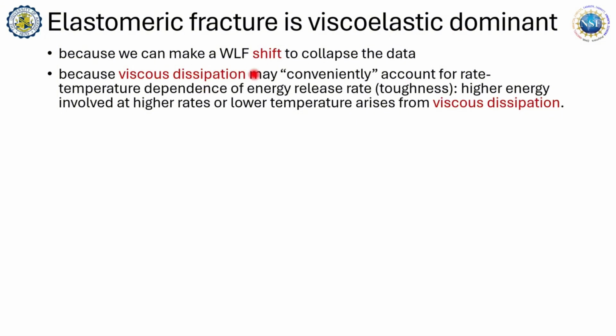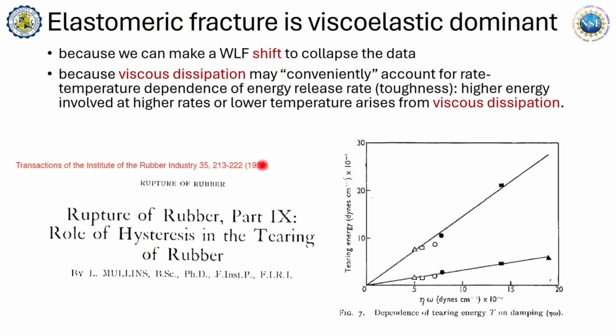Secondly, well, this so-called viscous dissipation, of course, is higher at higher rate and a lower temperature. Therefore, it conveniently seems to describe the rate dependence and temperature dependence of my resistance to fracture. That viscous dissipation will tell you. So in fact, one of the papers, 59, shows that it's just related to how viscosity increases as I go to lower temperatures. They have even added bonus that this view perhaps even can explain why my toughness, which is energy I need to pay per unit area, is much larger than surface fracture energy, because a lot of energy was consumed by dissipated processes.